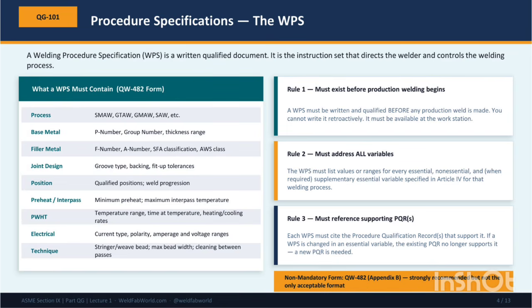The base metal, identified by P number and group number, with the thickness range qualified. The filler metal: F number, A number, SFA classification, and the AWS class. Joint design: groove type, backing, fit-up tolerances. Position: the qualified welding positions and weld progression direction.